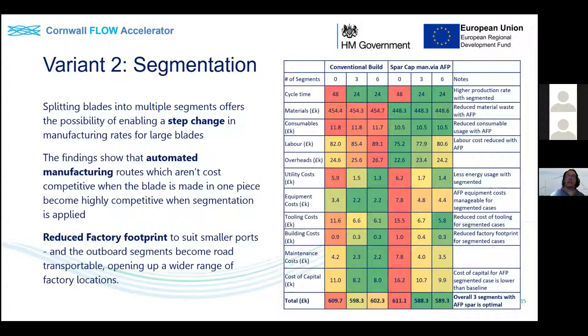And it gives flexibility of manufacture, because you can imagine there could be some ports, for instance, where you'd want the majority of the blade to be produced under a conventional mold. But if you have a segmented blade, you could either continue to manufacture at a local site or further afield within the country where those smaller segments are more easily road transportable. And that's a large cost burden to transport, but if you can reduce the size of them, it allows interoperability as well.